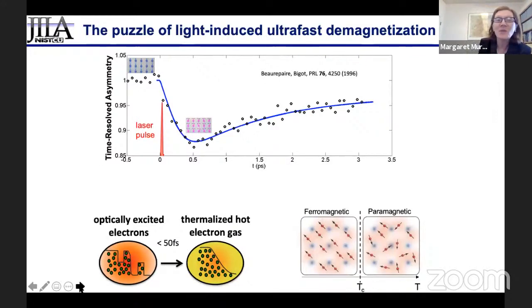magnetic systems. They've been looked at with femtosecond lasers since shortly after robust high power sapphire lasers were available. And this was beautiful work by Geneviève Bigot and Beaurepaire, where they excited a magnetic system, nickel, with the femtosecond laser and measured the magnetic asymmetry, which is the strength of the magnetic moment, with the same femtosecond laser. And what they saw is that it took quite a long time for the magnetism to decay.